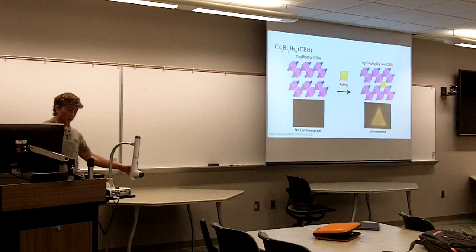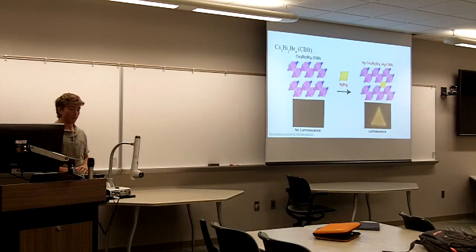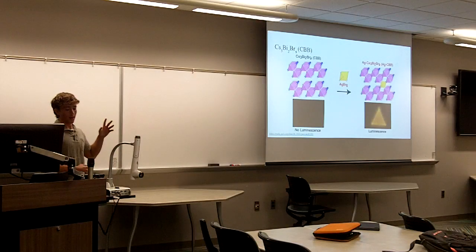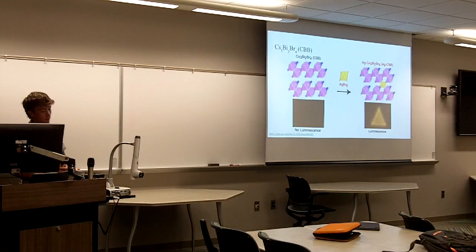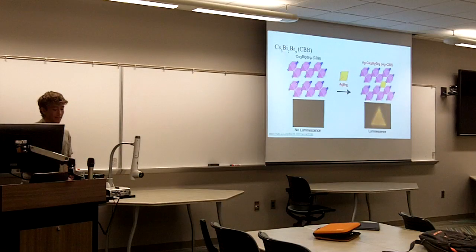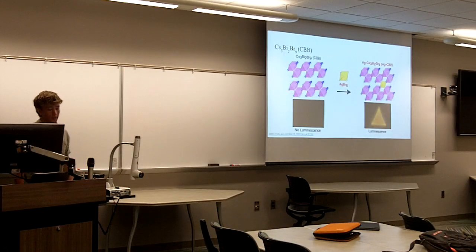My group previously worked on doping CBB with silver to enhance its PL properties, and by introducing silver into CBB via chemical vapor deposition, they created a vacancy-ordered layered perovskite that exhibits broad room temperature PL at 600 nanometers, significantly improving its weak PL. And the findings highlighted the potential of silver-doped CBB for advanced optoelectronic applications.